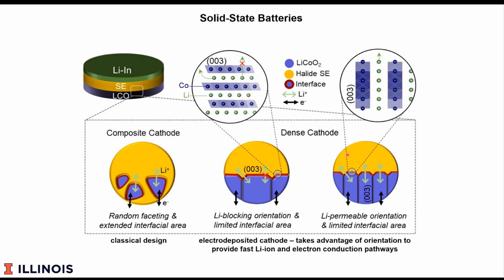So far, solid-state batteries have not been very successful for fast charging. Part of the problem is the way that we make solid-state batteries, that we use composite cathodes and either composite or metal anodes that don't work particularly well. The problem with the composite cathode is you're mixing the cathode with solid electrolyte. The structure has a high tortuosity. The kinetics of diffusion are somewhat limited. The interfacial area is high. There are sort of many problems.